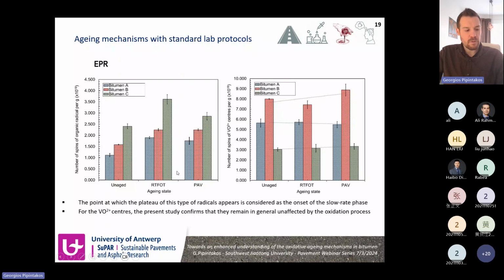And from the left graph, you can see that for all the binders we have an increase between the unaged state, so the fresh binder, and RTFO, and then a kind of stabilization of these carbon-centered radicals for binders A and B more specifically. And this again means that between RTFO and PAV, we have reached the plateau that was also observed in the kinetics. So we have reached the slow rate phase of a possible oxidation scheme. The vanadyl species were again, considering the standard deviation, almost stable with aging, and this again confirms the idea that this can be used as a tracer of the crude.